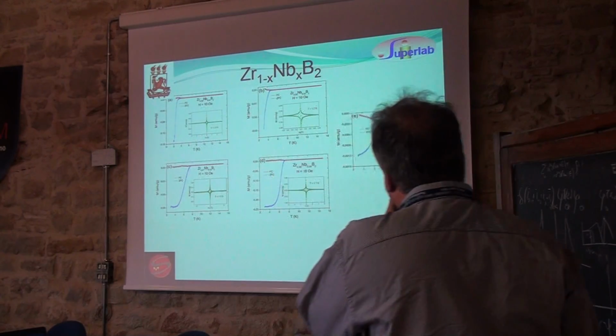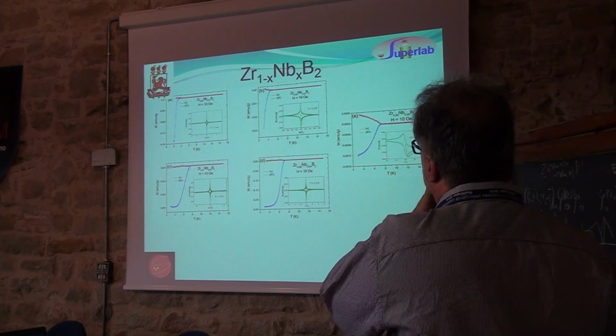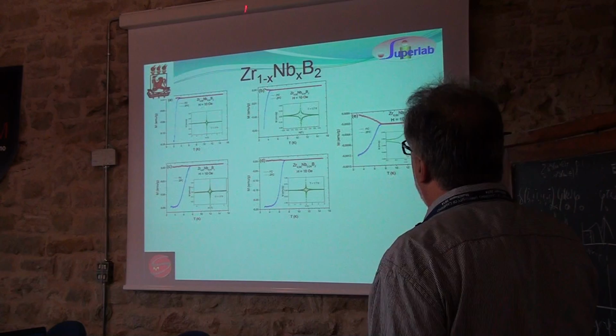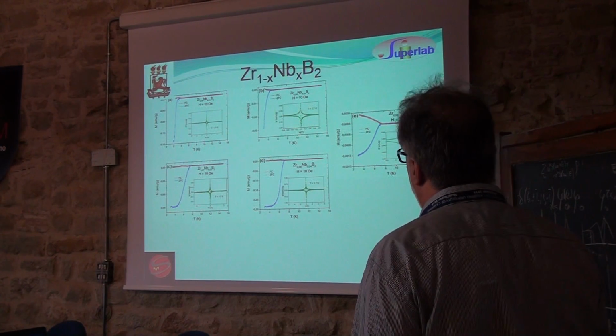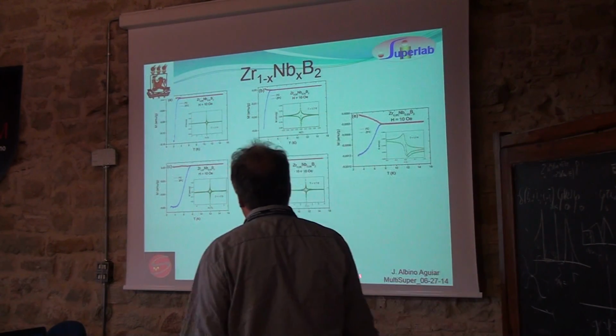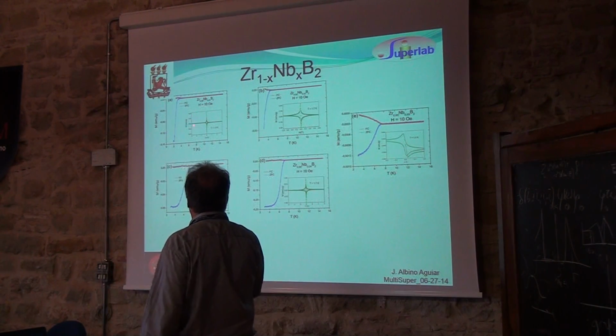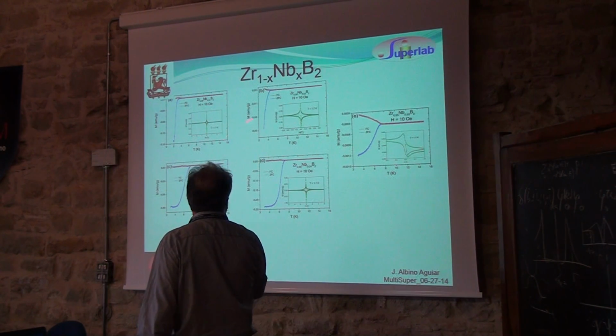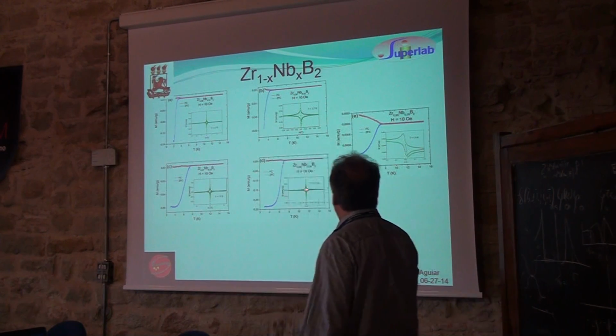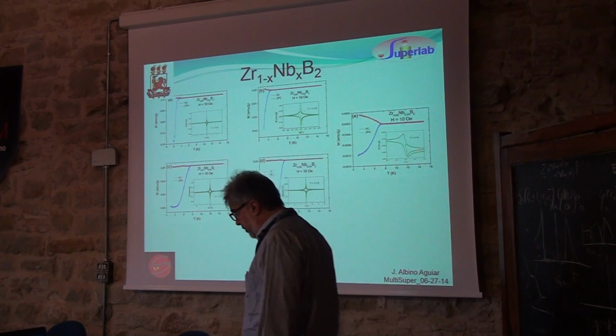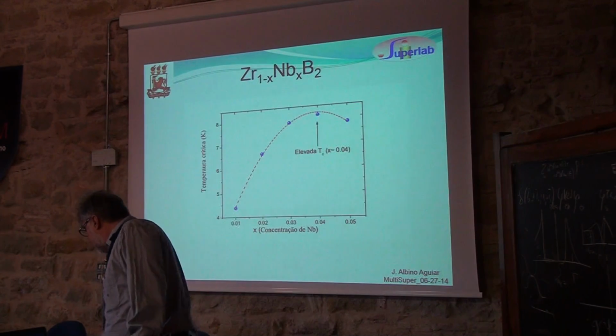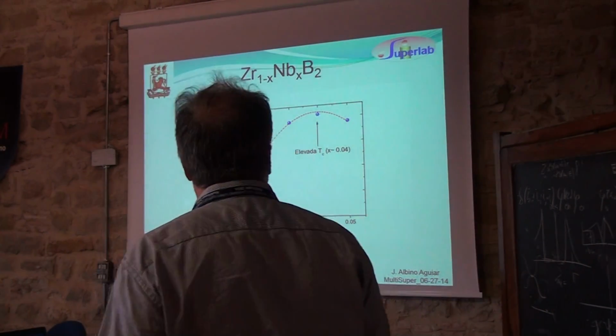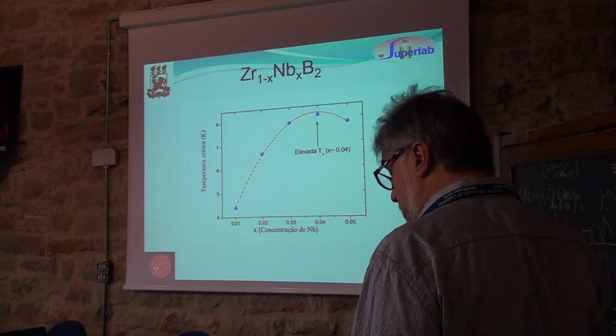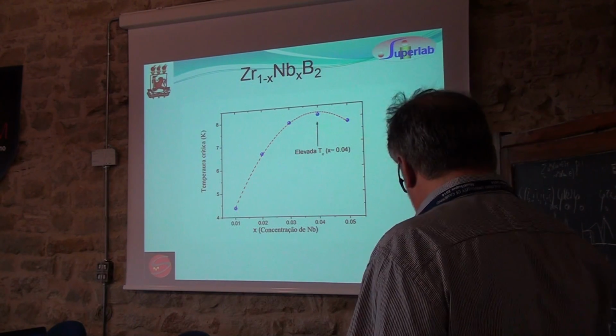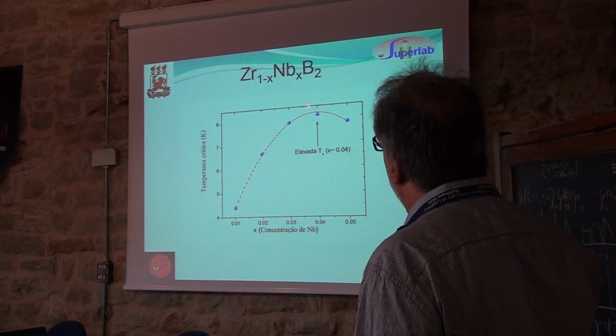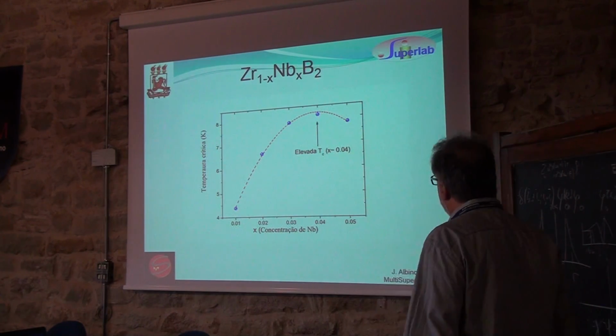So the magnetic data for this material, you see clearly that it is superconducting. So this is magnetization M versus H, all of them taken at 1.7 K. Again, here we have the transition temperature as a function of concentration, and it seems that for this concentration we have the optimum doping.